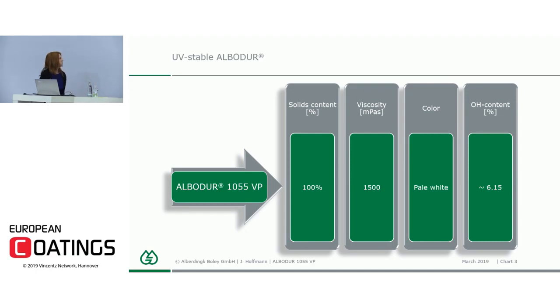Some key facts about the product. It is pale white, has a viscosity around 1,500 mPa·s, and an OH content of 6.15%. And that was one of the biggest innovations we did here, that we tried to create a resin which is relatively hard with a low demand of isocyanate, because the isocyanate part is normally in aliphatic systems the biggest impact on cost.